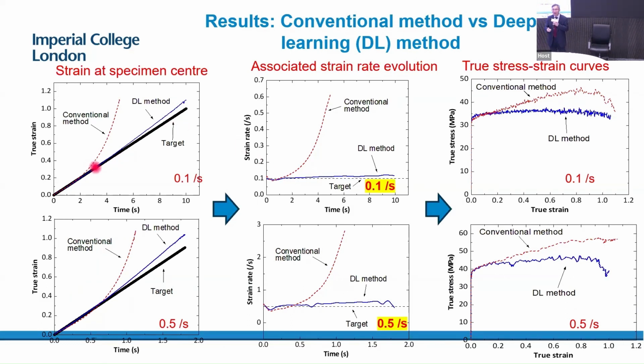Previously, for the conventional method, the true strain development is like this. If the target strain rate is 0.1, and we try to set 0.1, but previously the strain rate is like this. The error is up to 1000%. The error is very high. And if we set the target strain rate 0.5, conventionally it goes like this. But with this kind of learning process, we can get more or less close to this. The error can be controlled within 15–20%. It's difficult to get rid of the error, but compared to 1000%, this is a huge improvement.